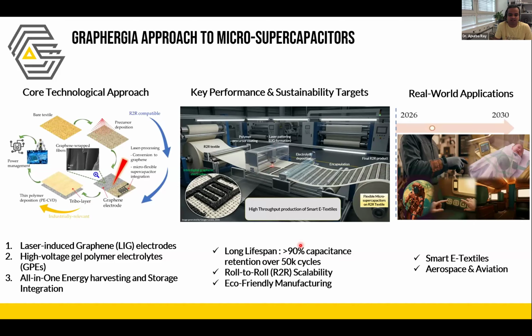And not only that, the roll-to-roll scalability, that means we are actively developing a fully automated pilot line under ambient conditions, a roll-to-roll pilot line for the digital production of graphene onto the textile, and also integrating this flexible micro-supercapacitor into this textile application.